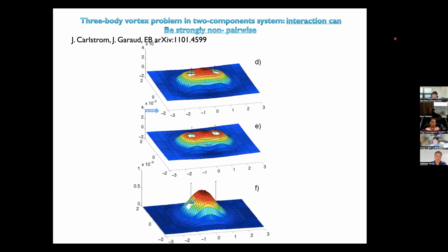But if we have these vortex clusters, they're tightly bound, and if we also consider fluctuations, then these nonlinear effects leading to three-body forces and four-body forces become important, and we calculated them. Since these are nonlinear effects, you can calculate them only numerically. This is an example where you pin two vortices numerically and bring in the third vortex, and you measure, in the lower panel, the difference between pairwise forces and real forces. You can extract the three-body forces, and they can actually affect structure formation in general.